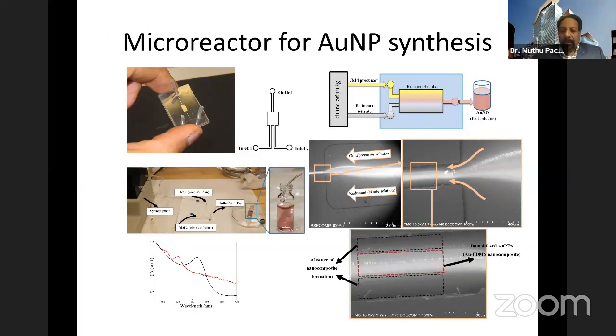What we do in an in situ synthesis, I want to give a very beautiful example here in microfluidics. Basically, you can see two channels. In one channel we pass a gold precursor, in the other channel we pass sodium citrate, which is the reducing agent. As the precursor and reducing agent interact, because of the microfluidic nature, the flows are generally laminar and Poiseuille flow. So they don't always mix, they mix only in the middle. As a result, you get nanoparticles produced in the middle, so you get beautiful streamlines of in situ synthesized nanoparticles.